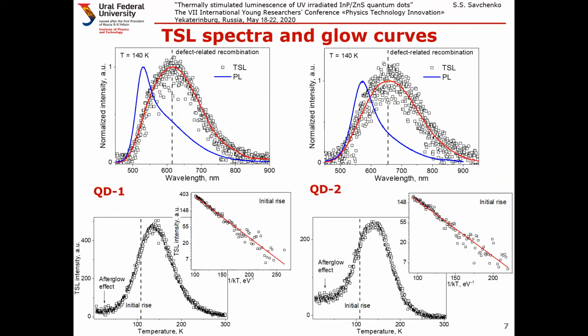To evaluate activation energy of the traps, low temperature interval of peaks has been analyzed with the initial rise method. Arrhenius plots yield the same energy values, about 27 millielectron volts. It points to the common origin of the traps in the studied quantum dot ensembles.